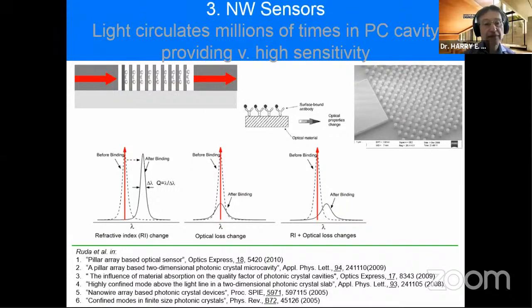One is by changing the refractive index, and remember it's dielectric contrast that's controlling the modal structure in these cavities. So by binding something to the outside of these rods, we change the effective refractive index of that medium. And so if you look at the left figure at the bottom, you'll see that the peak has shifted due to that refractive index change, with the peak width obviously reflecting the cavity Q. The other thing is that, of course, that material can absorb the light circulating in the cavity, which means it will damp it, so that there's an optical loss change which is pulling down the signal. So the general signal one sees is a combination of those two.